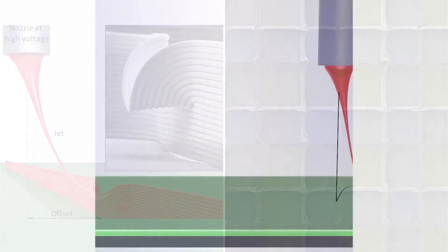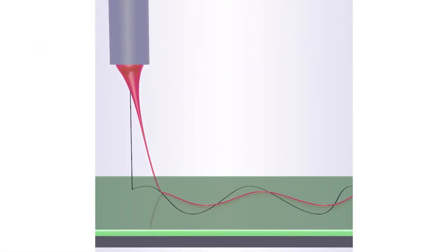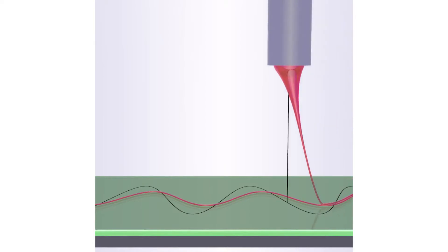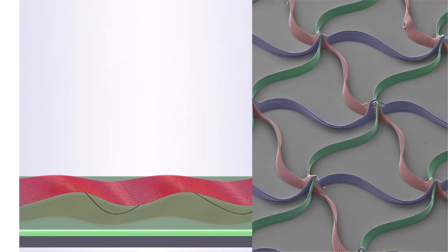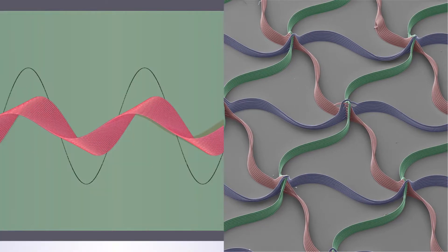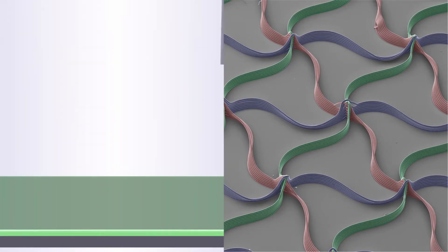It is known that printing above a certain speed causes jet lag. That is, the melt hits the collector surface a slight distance behind the nozzle, resulting in deformed structures. When printing sinusoidal waves at such speeds, the jet lag causes the stacks to become tilted as layers are added.